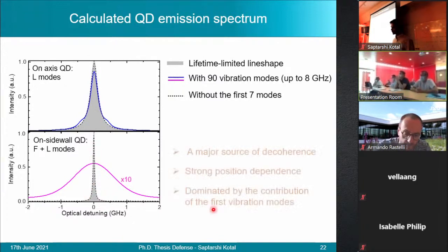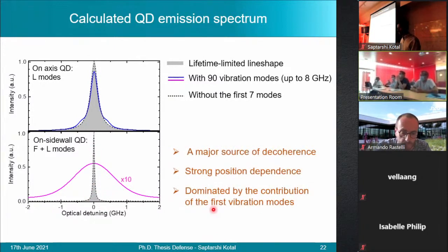So from this, we conclude that yes, the vibration modes are a major source of decoherence in a quantum dot embedded in a nanowire. This source of decoherence is strongly dependent on the position of the emitter, and it's dominated by the contribution of a finite number of low frequency modes.